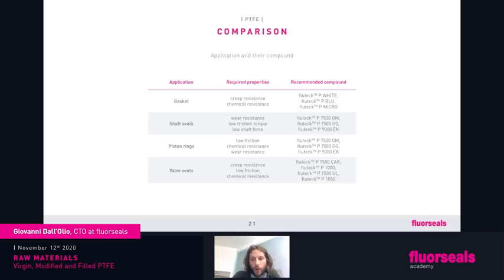And what we really want to show you with this slide is that sometimes when an application comes, for example, a shaft seal on the second row, we understand that for that application we need a very good wear-resistant material, with low friction torque, so the friction on the first movement, the static friction, has to be low, and the shaft force also low because it's a dynamic application. We have different materials that work, like for example glass moly, so fluteck P7500 GM is a 20% filled glass plus 5% moly, MoS2. This is a great compound. No wonder, it has a very good behavior.